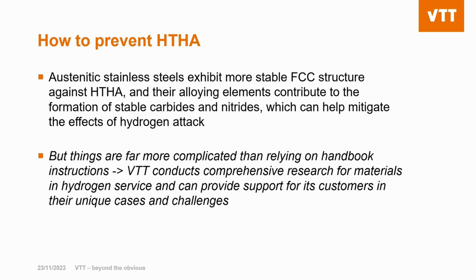Austenitic stainless steels are better. They exhibit a more stable face-centered cubic structure against high-temperature hydrogen attack, and their alloying elements contribute to the formation of stable carbides and nitrides, which can help mitigate the effects of hydrogen attack. But in industrial applications, things tend to be far more complicated than relying on these kind of handbook instructions.